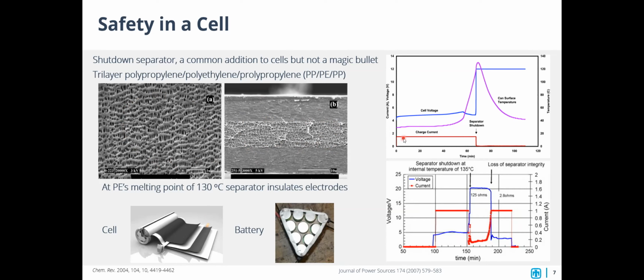In this graph up here, we see charging of a cell in red at a certain current, and the temperature increase in purple, where we hit a temperature at which our shutdown separator melts, and we get the stop of current flow. This is a way of ensuring that your system won't develop internal shorts through the separator above a certain temperature. Unfortunately, while this works very well at the cell level, it's not perfect. It's been shown for battery packs that have higher voltage tolerances that even after the shutdown of the separator at a high temperature, the separator itself can degrade due to the high voltage, reopening ion channels and allowing current to flow even at high temperatures. So a good solution for single cells, but imperfect for battery packs.